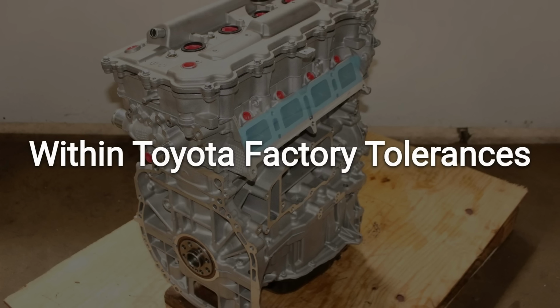Finding number 4, the timing chain and its tensioner. This is a component Toyota engineers specifically overbuilt because a stretched timing chain can throw off valve timing and trigger a cascade of drivability problems. We measured chain elongation on both engines using a chain wear gauge against a fresh reference chain. Car A's timing chain showed marginally more stretch, roughly the difference you'd expect from maybe 3,000 to 4,000 additional miles of wear equivalent, even though both cars had identical mileage.